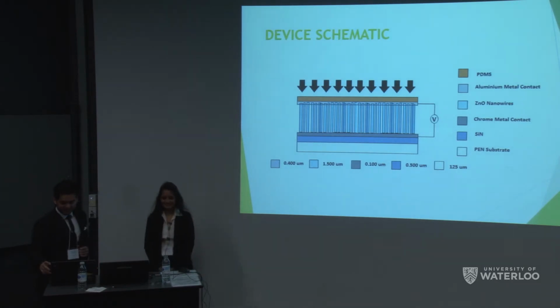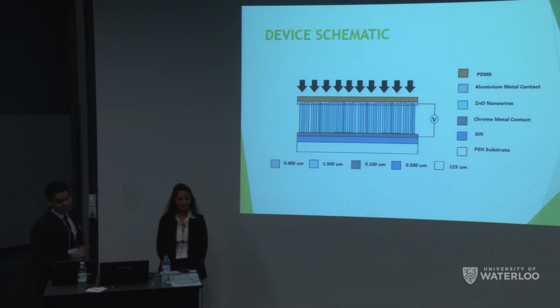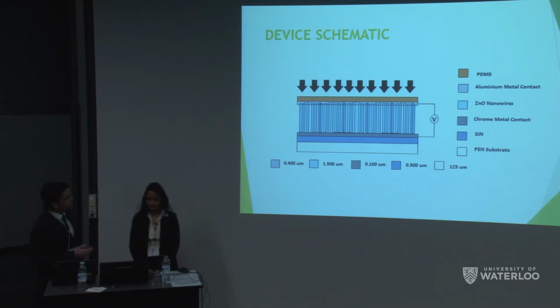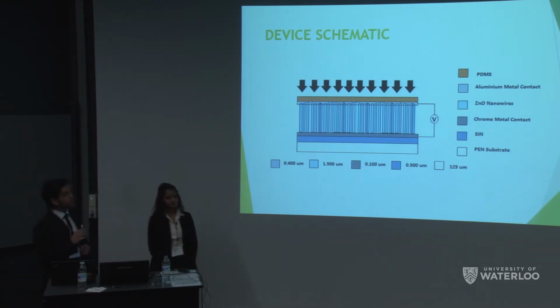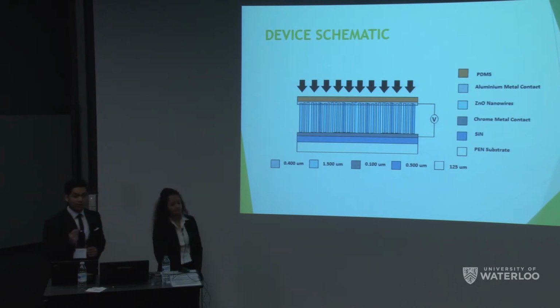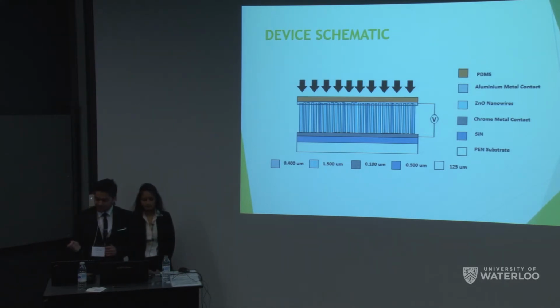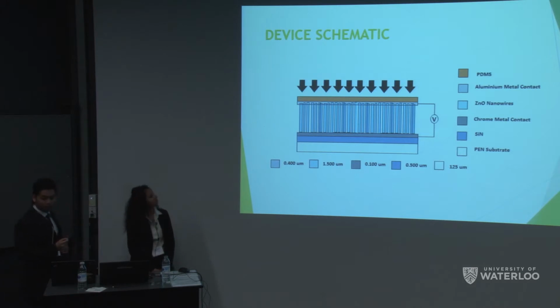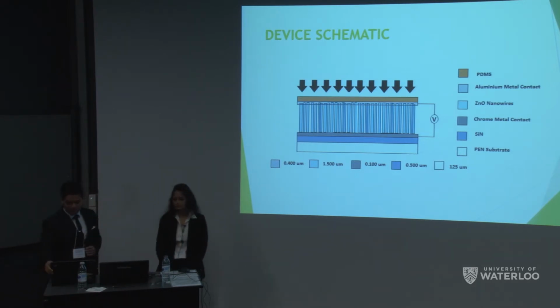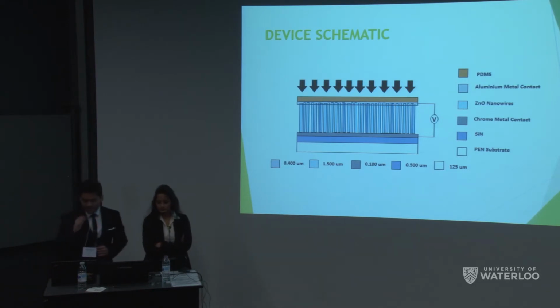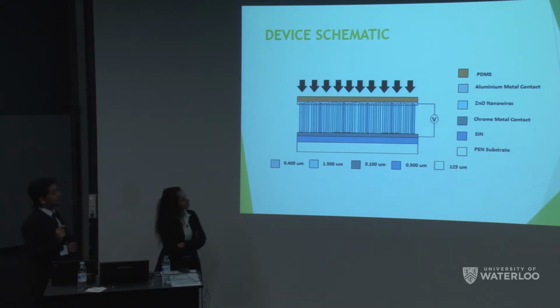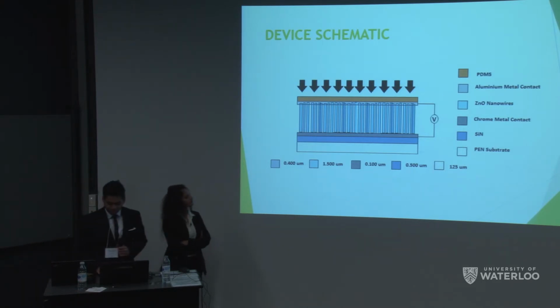So just to give you a brief idea about our masterpiece, this is how it would look if you zoomed into it sideways. At the bottom, we have our flexible PEN substrate coated with silicon nitride for added sturdiness, on top of which we have our bottom chromium electrode. And the light blue region that you see here is our zinc oxide nanowires, our piezoelectric layer, and on top of which sits the top electrode and a PDMS layer for insulation.